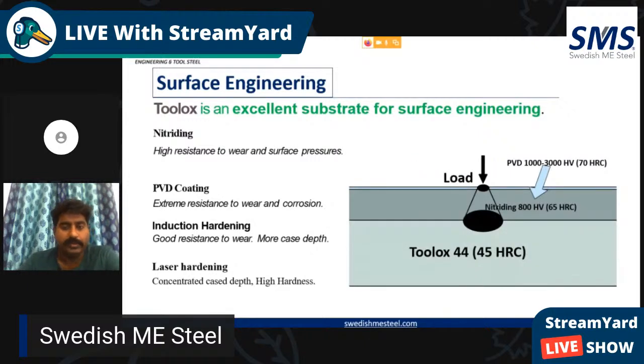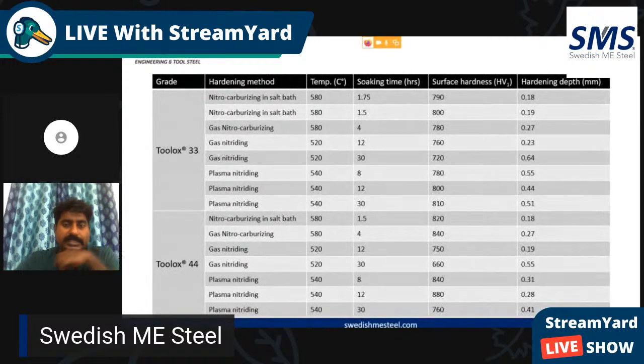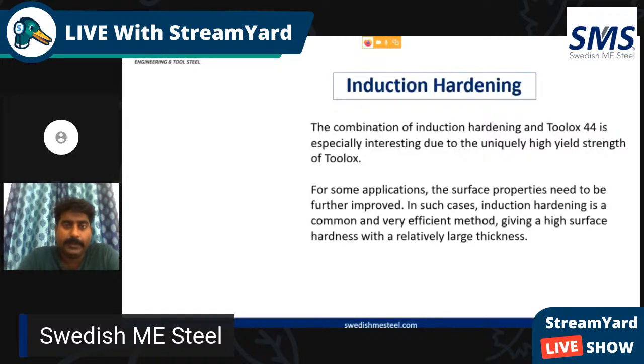So Toolox is delivered at 45 HRC. When you do nitriding, you'll find the hardness values increase from 60 to 62 HRC. If you do PVD, it will cross 70 plus in hardness. So this is a general chart showing the different temperatures you need to maintain and different soaking times for you to achieve surface hardening and the desired hardening depth. You can use this sheet as a reference.